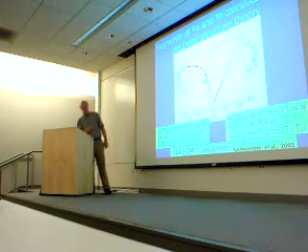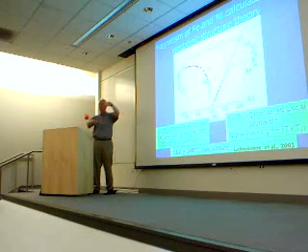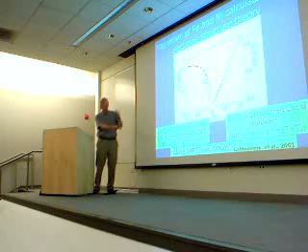If you look from the right-hand side, you expect the Curie-Weiss susceptibility. So the susceptibility is 1 over temperature minus the Curie temperature. So the inverse susceptibility, which is what this is, goes to 0. The susceptibility goes to infinity.